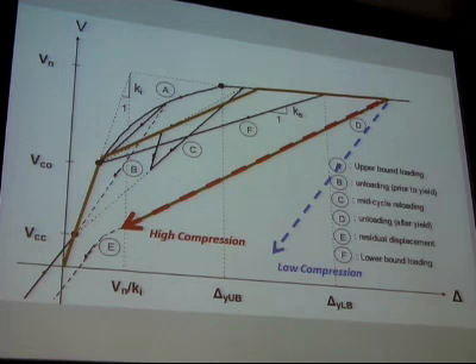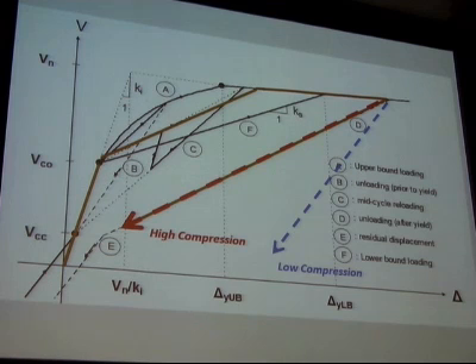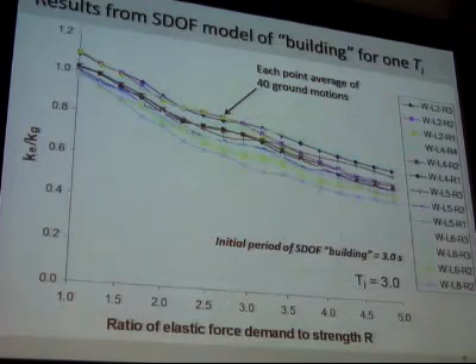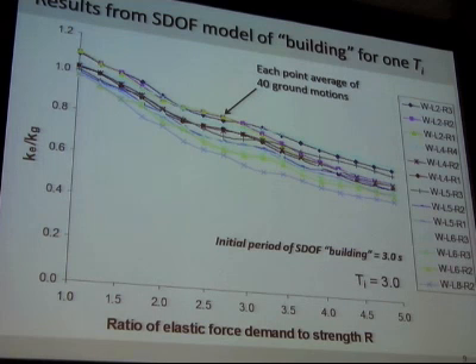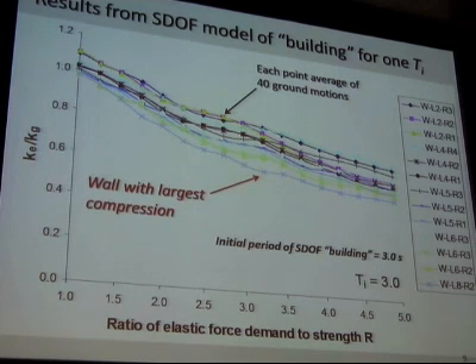But if you look at the full response, and in particular if you look at the hysteretic response, what happens is a wall with high axial compression has very little energy dissipation, because when you take the lateral load off, it stands up straight. Whereas if you've got lower axial compression, you dissipate more energy. You get more hysteretic damping. And that turns out to make a huge effect. And here are some analyses we've done. And these are simple single degree of freedom analyses, many, many different shear walls. And the really interesting point is the walls with the highest compression have the lowest effective stiffness.